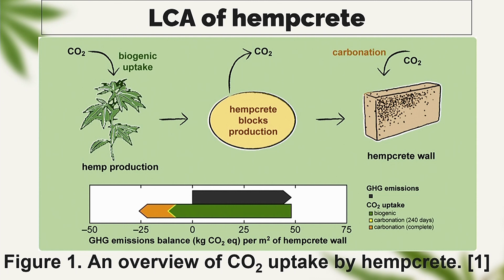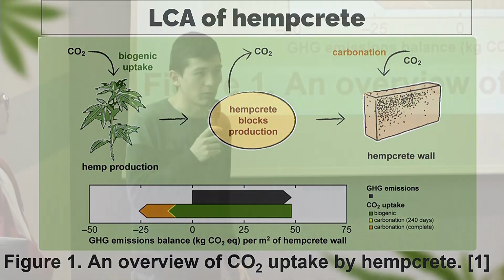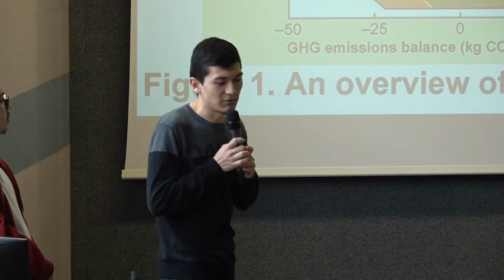In the chart below, you can see the greenhouse gas emissions balance per square meter of hempcrete wall. The black line above corresponds to the greenhouse gas emissions, while the orange, yellow, and light green lines correspond to the CO2 uptake. As you can see, there is much more CO2 uptake than greenhouse emissions. That means there is a negative carbon footprint, which is favorable.